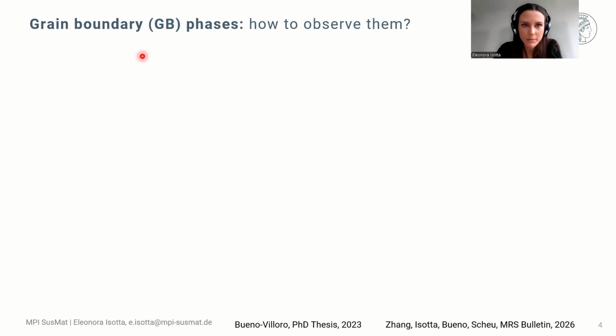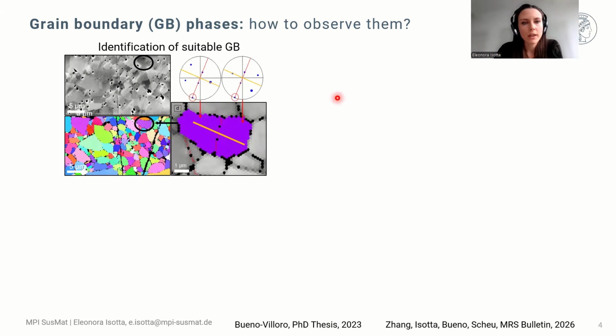So we have seen what grain boundary phases are. Now let's see how to observe grain boundary phases and the transitions between them using high resolution methods. When we want to use high resolution methods, we typically start by identifying a suitable grain boundary using lower resolution methods, for example SEM imaging or EBSD, electron backscatter diffraction, which allow measuring a large area of our samples.